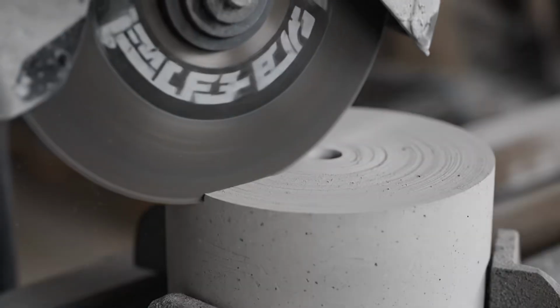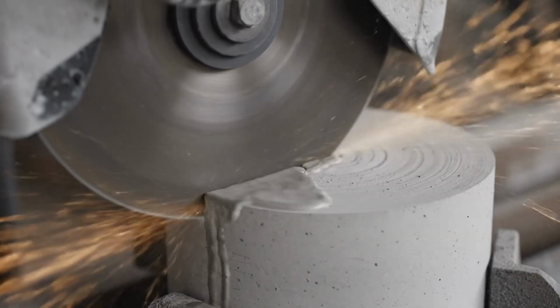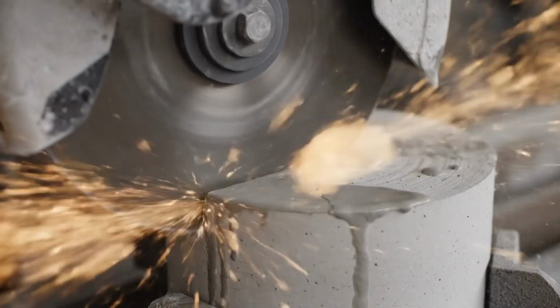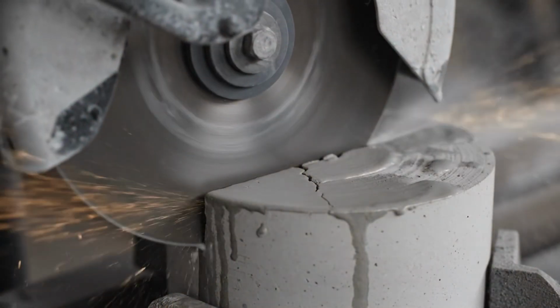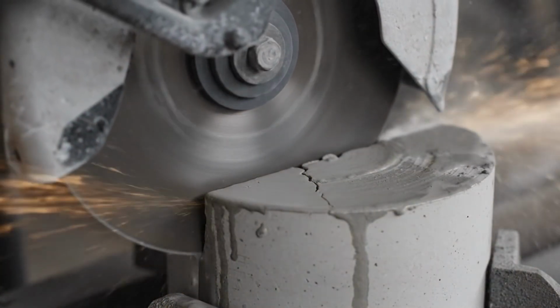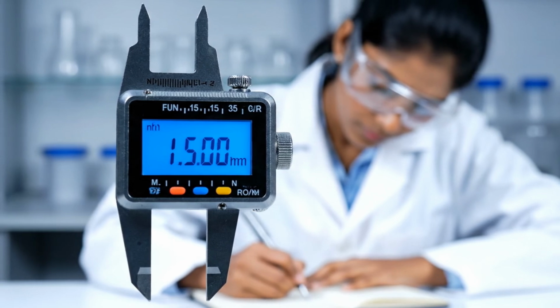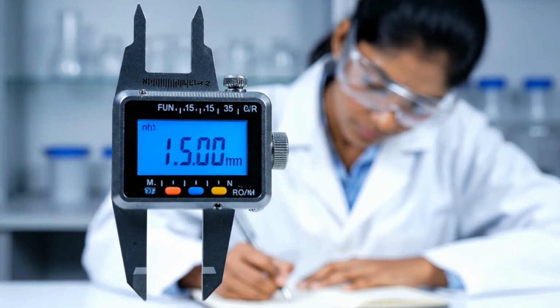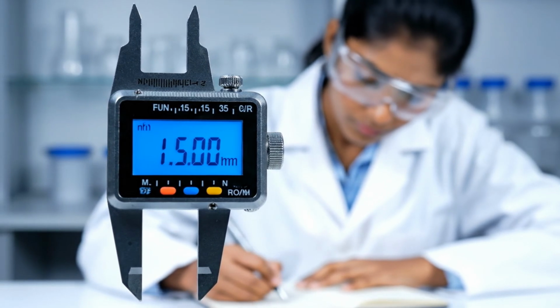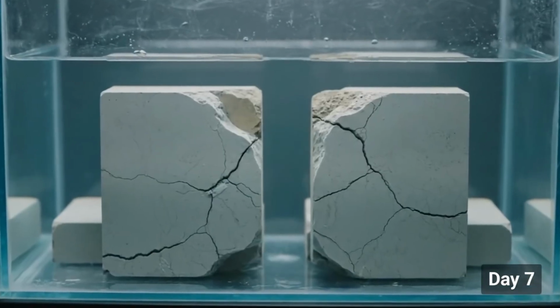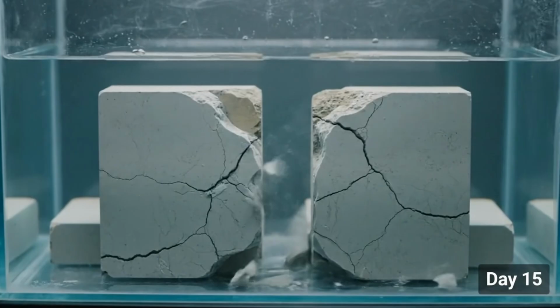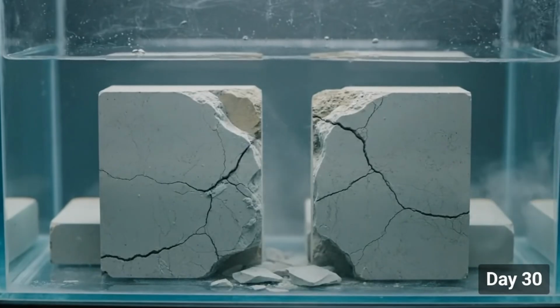The team used a diamond saw to deliberately crack their samples. They measured crack widths with precision calipers, 1.5 millimeters exactly. Then they submerged the cracked concrete in water tanks and waited. Days became weeks. Nothing visible happened. Had it failed? On day 30, they removed the samples and examined them under microscopes.